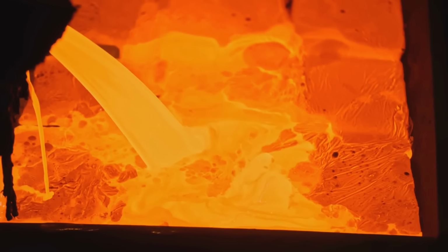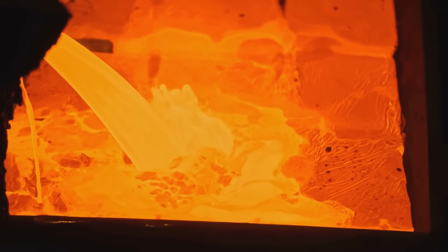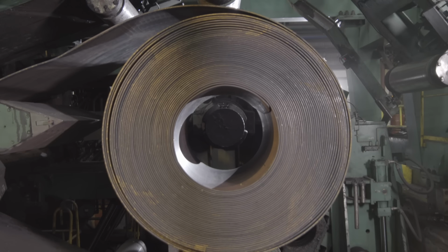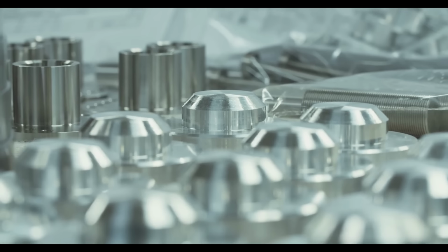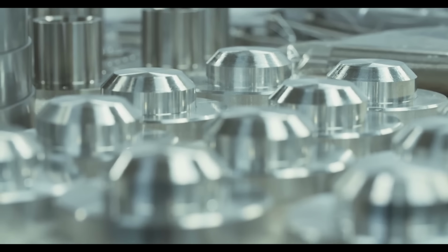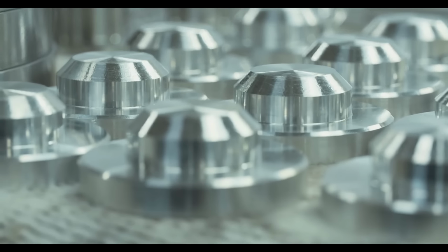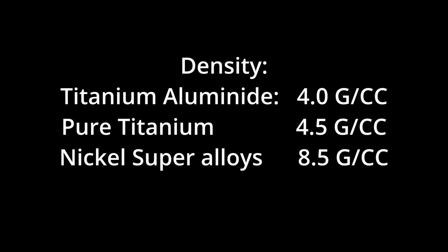When titanium and aluminum are combined in certain fixed ratios, they form intermetallic compounds such as titanium aluminide and alpha-2 titanium aluminide. These are not just random mixtures, but ordered compounds. So, what is so special about them? Well, they are extremely lightweight, even lighter than typical titanium alloys, and can withstand high temperatures better than normal titanium metal. For example, titanium aluminide has a density of around 4 grams per cc. Pure titanium is about 4.5 grams per cc, and nickel superalloys are 8.5 grams per cc.